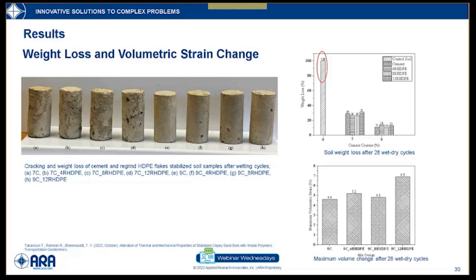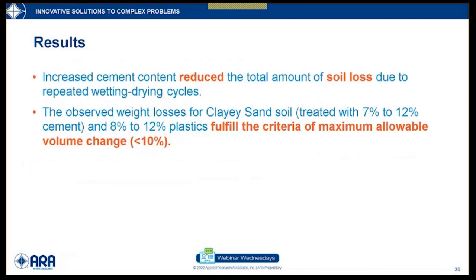And the maximum volumetric change observed after 28 wetting and drying cycles is shown in this figure, with a minimum of 4.6 and 4.8% of volumetric strain observed when 9% cement and 8% regrind HDPE flakes were used. The Portland Cement Association says that when the volumetric change is less than 10%, it fulfills the performance criteria. It can be applied in the field and is observed to perform satisfactorily.